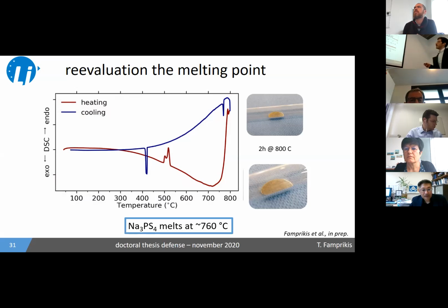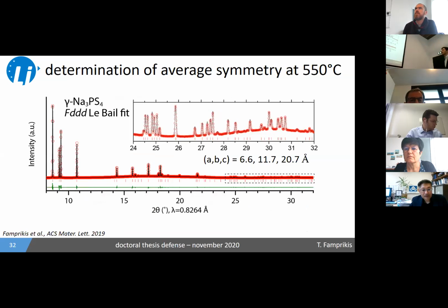Now, going back to the structure, the diffractogram at 550 C can be fit very well with an Fddd symmetry and these lattice parameters here. I would like to highlight once again the wavy nature of diffuse scattering shown in both panels here, as well as the rapid diminution of the peak intensity, which is linked to high disorder in the structure, typically modeled with B factors, the Debye-Waller factors.